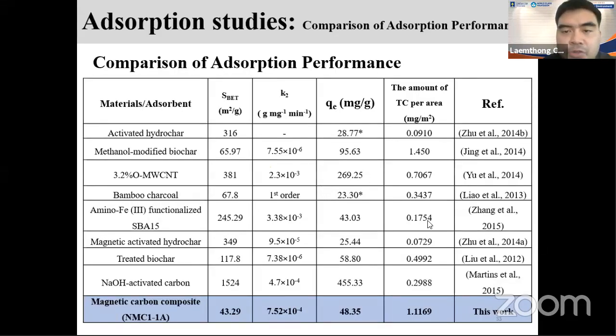But compared to the other work in terms of amount per area, we actually have a higher value. That means you have the amount in terms of the area, because we have quite a small area for these cases. This is still quite challenging, so we have to produce more with the HTC technique, which can result in the carbon adsorbent that already has a high surface area. But so far, we can obtain only a maximum of about 50 square meters per gram. This is still quite challenging for our purposes here.